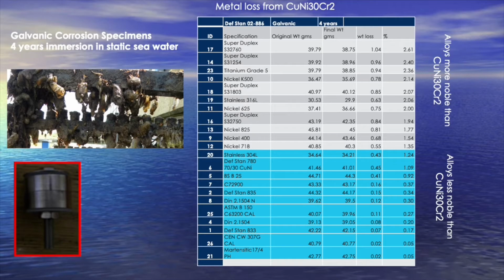Here we have the percentage metal loss over the 4-year time frame of all of these alloys. We can see that some of the alloys in particular were very, very good, and some were surprisingly poor. So this was the galvanic comparison. So every other alloy was galvanically coupled with copper nickel chromium to assess the compatibility. And we can see that everything in blue would be classed as compatible with copper nickel chromium.